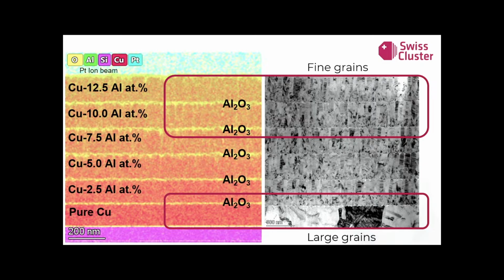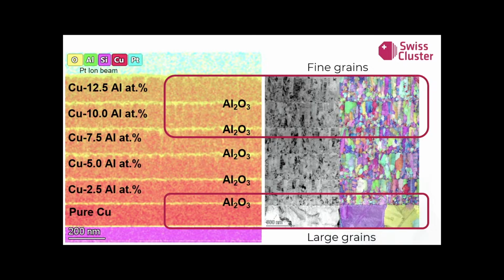He deposited pure copper. You can see the large grains in these TEM images, and adding aluminum from 2% to 12%, you can see how this gives a grain size refinement independent of the addition of the ALD layers. You can see the aluminum oxide in between, separating the different multilayers, but the grain size remains the same just because of this solid solution.